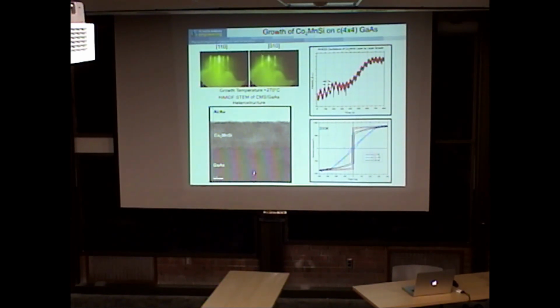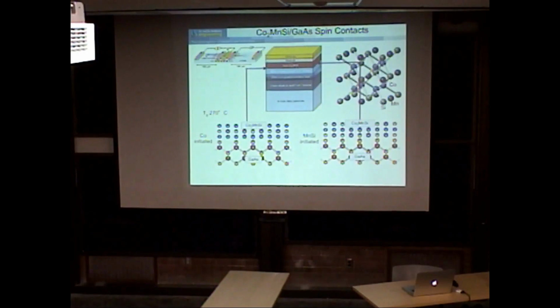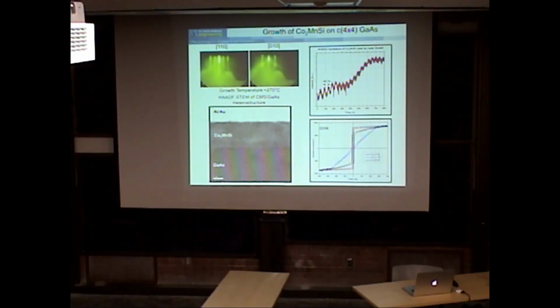Here's a cross-sectional TEM image. You can see the gallium arsenide. Here's the cobalt manganese silicon. If you look very carefully, you might see it looks slightly different up here than it does down there. This checkerboard pattern is a little different. This is primarily L21, which is a Heusler structure. This down here is B2, as we can tell. Magnetically, we have uniaxial anisotropy, with the easy axis along the 110. These are RHEED oscillations that suggest layer-by-layer growth while we're growing it. That's in plane? In plane, these are all in plane.